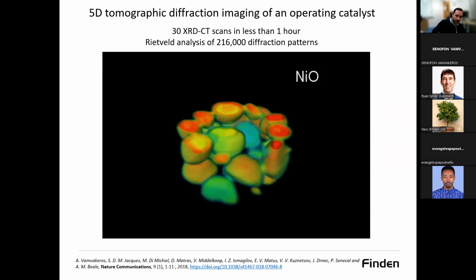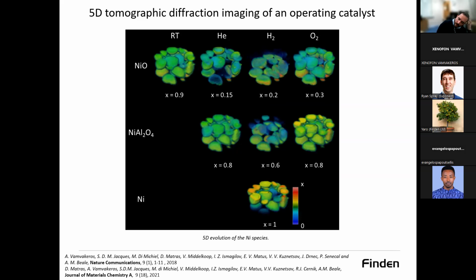Back in 2018, we performed the first 5-dimensional experiment. So we tried to do this 3D chemical imaging under different operating conditions. This was not a battery, it was a catalyst, but the technique is the same. So in this case, what were the 5 dimensions? You had X, Y, Z, 3 spatial dimensions. You had the scattering angle or reciprocal space, if you want to think about this. So that was the chemical dimension. And then the 5th could be time, so temporal, or imposed chemical environment.